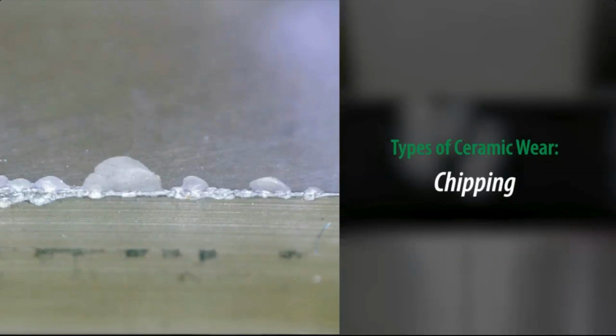This next image shows chipping. Chipping is often a result of vibration or instability, and it could mean that the tool is encountering large inclusions along the cutting path that are different or harder from the rest of the base material. Chipping leads to the uneven distribution of mechanical stresses and heat along the cutting edge and can lower tool life. Prolonged chipping may lead to our next type of wear, flaking.